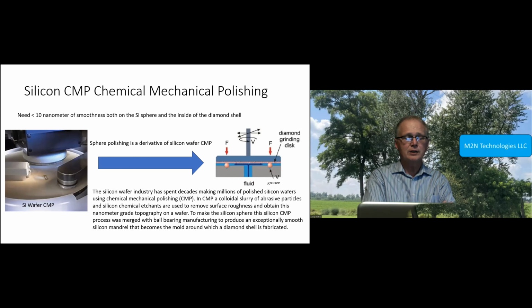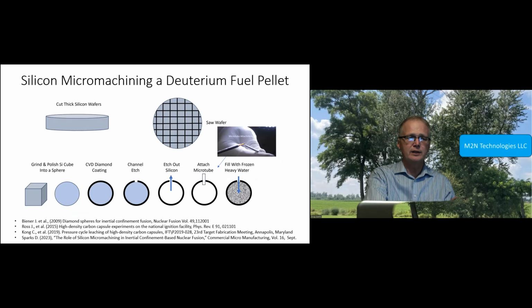So you have a polishing pad, but the spheres are sitting in grooves on the bottom. You get this counter rotation, with the spheres rotating, and with this colloidal, chemically reactive slurry, you chemically and mechanically etch away all the surface abrasion, scratches and roughness. You've got to get down to less than 10 nanometers of smoothness. And this shows you the total fabrication flow. You've got to get the interior of that diamond sphere extremely smooth, so you have a uniform compression of the fuel.